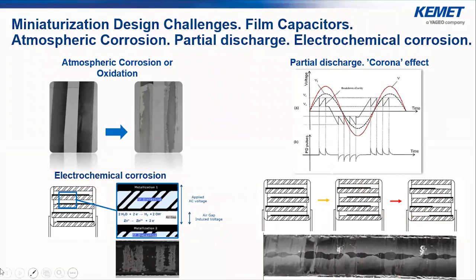Aluminum or zinc electrodes with an oxide layer on the surface may suffer electrochemical corrosion. Especially when the surface of the oxide layer has defects such as scratches, cracks, and other impurities, local corrosion is more likely to be induced. The local corrosion is likely to expose the base metal because the metal is in the active state, and the undamaged oxide layer is in the passive state. In that case, an active-passive corrosion battery is formed so that corrosion can be produced. The electrochemical corrosion rate of a metallized film capacitor is affected by factors such as operating voltage, operating temperature, ambient humidity, and also the electrode material.